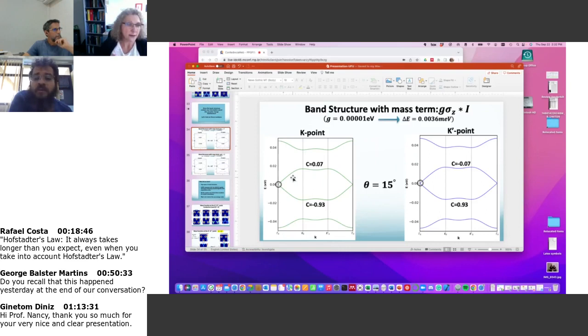The reason was because we were hoping to see Landau level scaling between these bands, and we didn't find Landau level scaling because we were biased with this picture that when you have a strain, you have Landau levels, and that picture is wrong. When your strain is inhomogeneous, what you have is magnetic barriers, magnetic field dependent on the position, and that will not give you Landau levels.